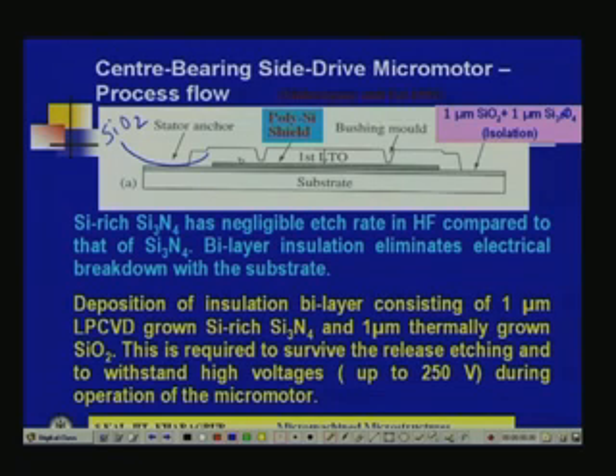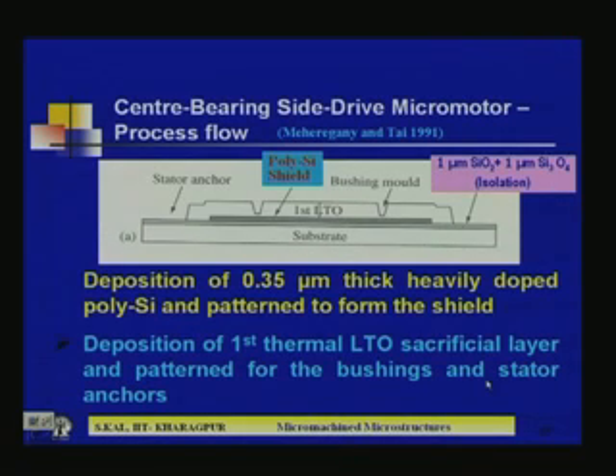So, this is the bilayer you have used here, the silicon dioxide and silicon nitride LPCVD grown, that is the insulation bilayer. Then you go for, because this silicon dioxide silicon nitride bilayer structure has been used to withstand high voltage, because between stator and rotor the voltage may go up to 250 volts. So, that is why not only oxide but the oxide and nitride combination has been used. Okay. So, nearly 250 volts it can withstand, and after that you go for patterning other layers.